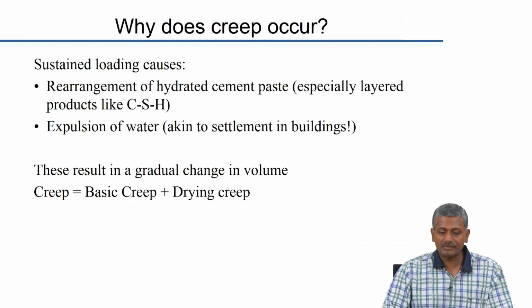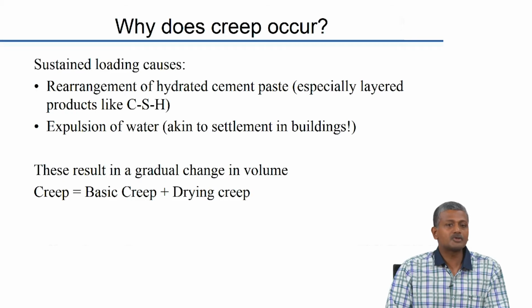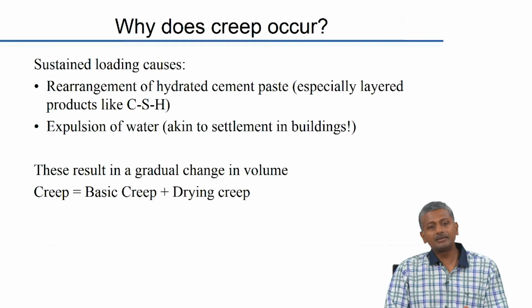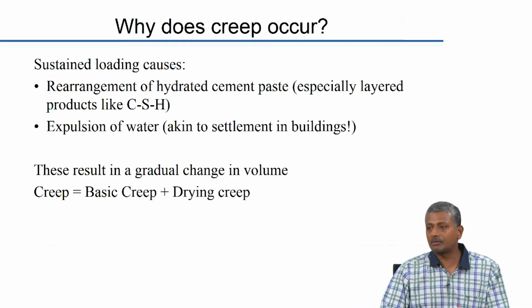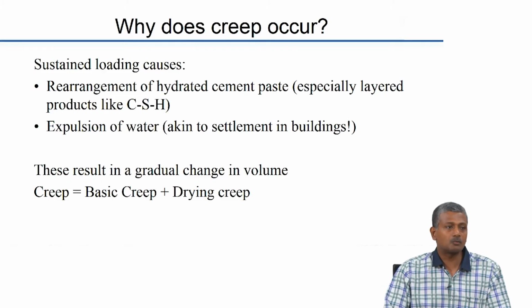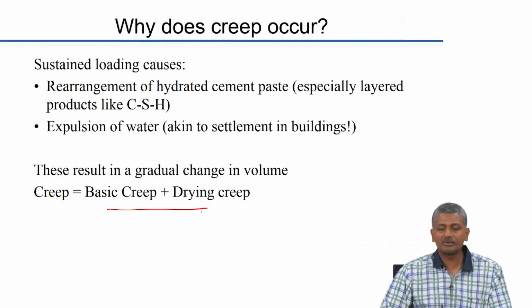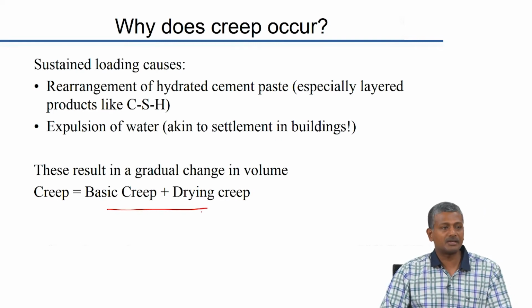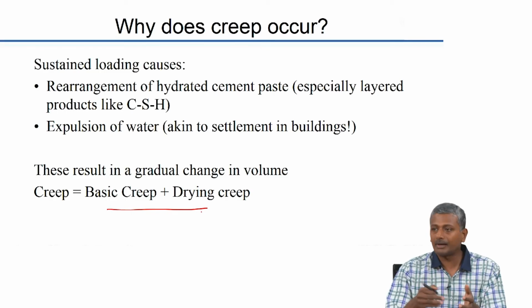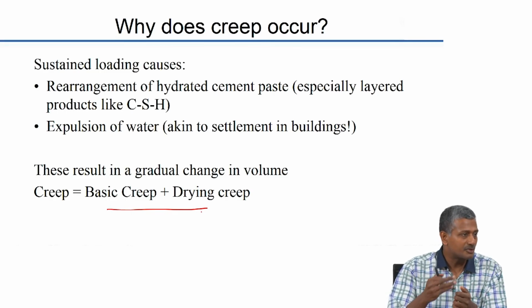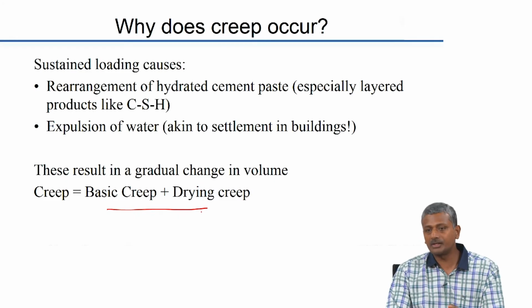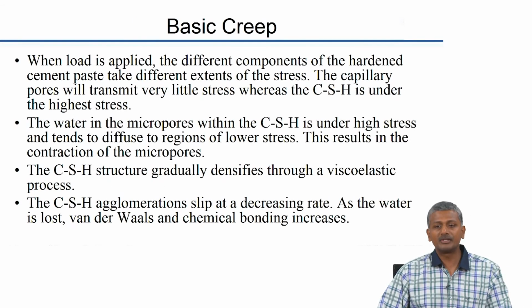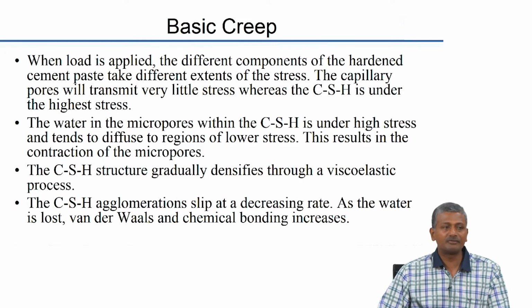Sustained loading basically causes rearrangement of a hydrated cement paste, primarily because you have layered characteristics of CSH, and there will be expulsion of water from the system, either from the concrete itself or within the concrete water is occupying other spaces than it was earlier. So, this results in a gradual change in volume. So, as I said, creep is composed of two components. You have the basic creep and the drying creep. Basic creep is entirely because of internal rearrangement. Drying creep happens when this is exacerbated because of removal of water from the concrete because of drying conditions existing. So, again the mechanism is explored in more detail on the slide. So, when load is applied, different components of the cement paste take different extents of the stress.